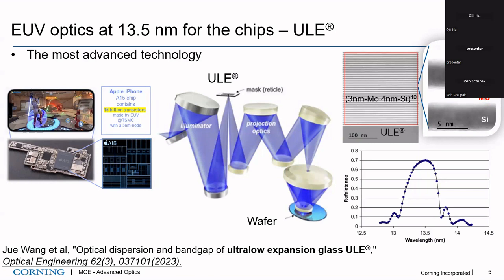So this is a TEM image on the upper right. You see the periodic molybdenum silicon structure to get a higher reflectivity at 13.5. Each individual layer is only 3 nanometers and 4 nanometers. So the challenge is that the best reflectivity is around 70%.